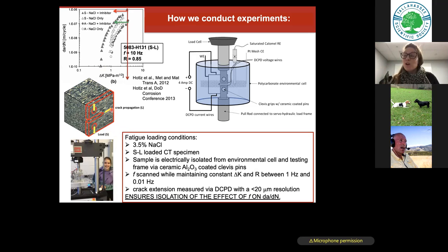When we grow a crack, it will cause a resistance change. And so we measure the voltage out here, right in the crack mouth. We can measure voltage changes and then translate that voltage change to the resistance change, and we can then translate that into a crack length change through certain equations that are calibrated based on your sample type.